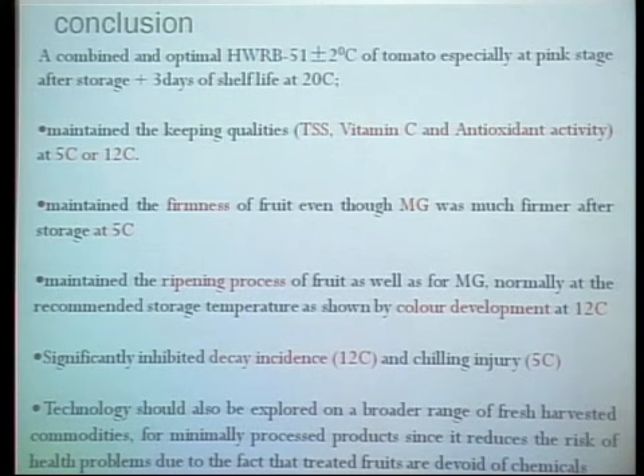Now, in literature, we noticed that the TSS and the color had somewhat of a correlation, in the sense that as the fruit ripened, the total soluble solids also increase. But if the fruit doesn't ripen so much, it also has some effect on the total soluble solids. And for the vitamin C and the antioxidant activity, we noticed some kind of correlation, even though I didn't put it here, but it wasn't something that I was so much interested in.